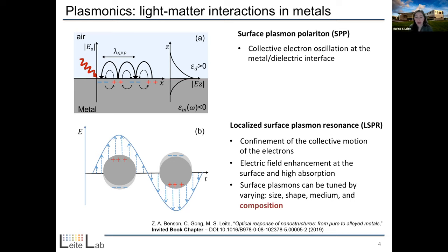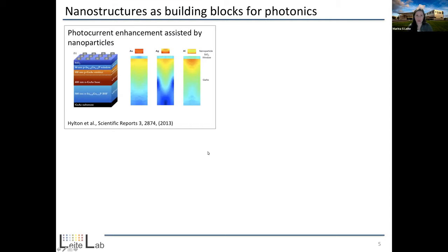Now, historically, there has been an enormous amount of really good work where people have managed to control light absorption by using metallic nanostructures that have a variety of geometry, size, and also by varying the medium in which these nanostructures are embedded, the metal that makes this building block itself. However, chemical composition has been a parameter that has been, I would say, somewhat overlooked. And then we decided to focus on that, and I will basically be telling you what has been our contribution on the field on that.